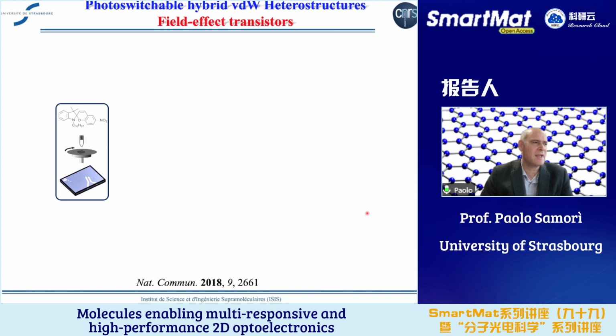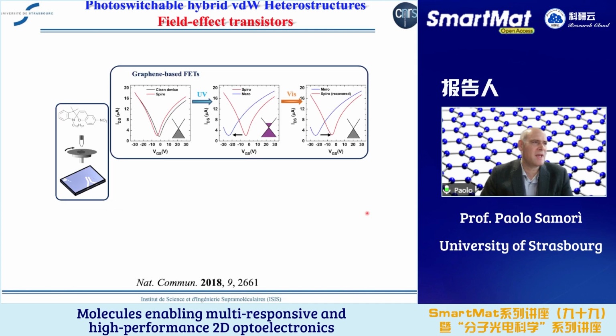Of course, we're interested in the electrical characteristics, and the idea here is that we spin-coated the spiropyran on the basal plane of graphene, and already you can see we can compare the pristine, so clean graphene device, with the spiro. We have a small n-doping effect, you can see with the red curve. If you irradiate with UV light to trigger the isomerization from spiro to mero, the n-doping effect is major, and you obtain the blue curve. But with visible light, actually, you recover this n-doping, and you go back to the initial spiro curve.